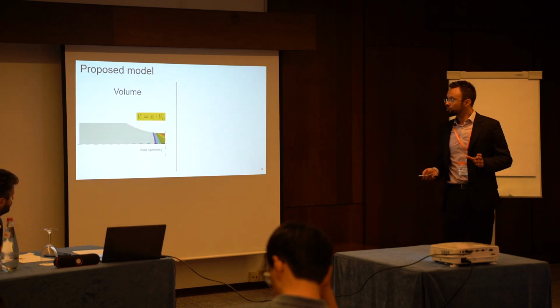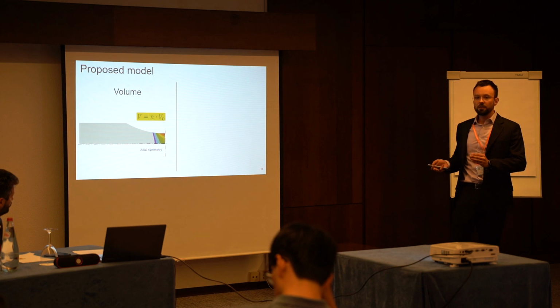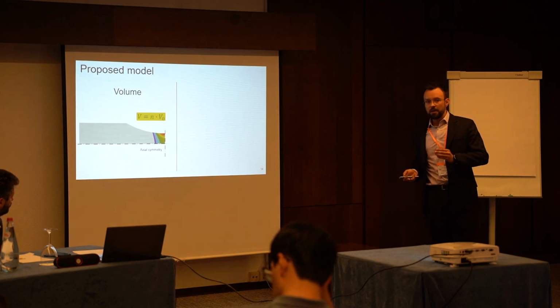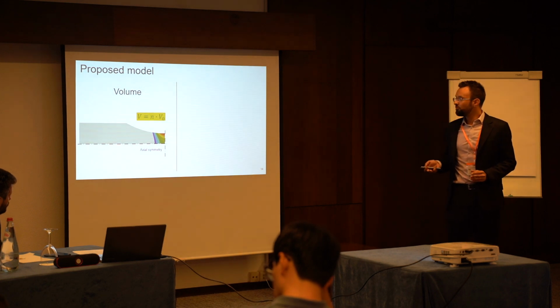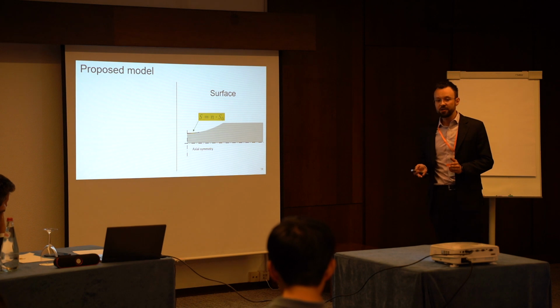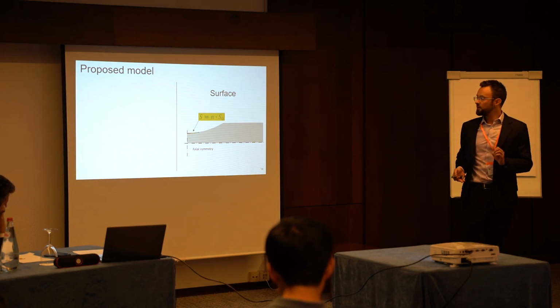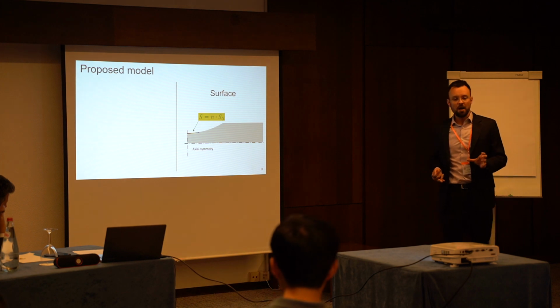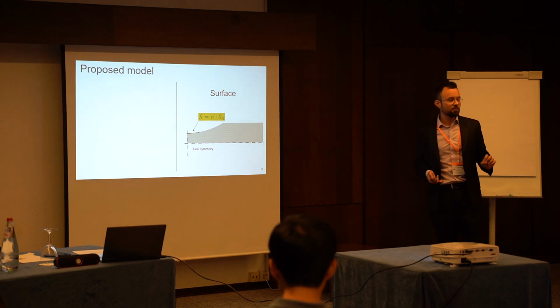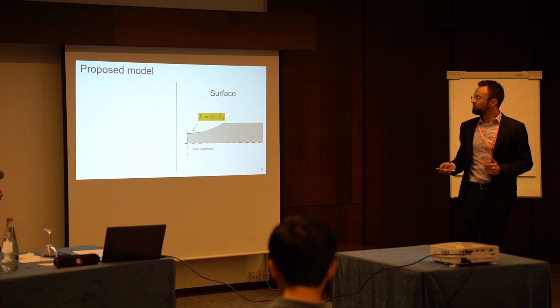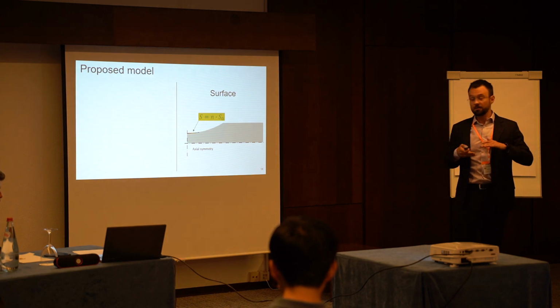As with the length, here we can also see that the large volume is equal to n times the small volume. The same holds for the highly stressed surface. The surface case is studied due to the fact that volume imperfections usually lead to cracks at the surface.